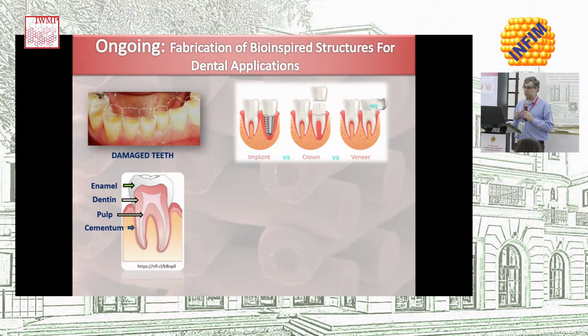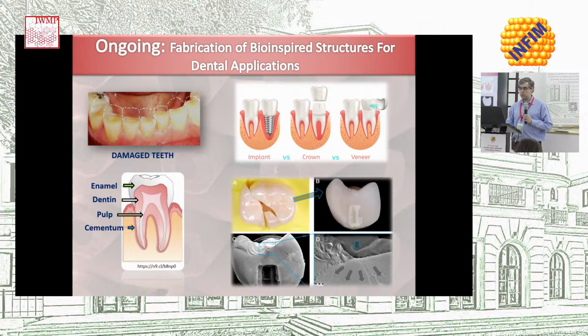And what the dentist can do is basically replace this external part of the teeth that has been damaged with a crown or a veneer, which is basically a very hard and brittle ceramic material, put either on top of the remaining teeth or some implant, on the outside. And even though these materials are much harder, much stronger, and stiffer than the initial enamel, they still fail.